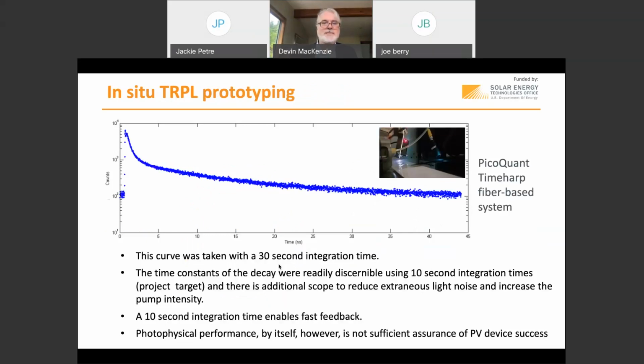We prototyped a PicoQuant fiber-based system. The real key for TRPL was, could we do it fast enough? Could we get enough signal? Our target was a 10-second integration time. So we integrate for 10 seconds, and can we reliably measure a tau, a reproducible lifetime? Because that would enable us to change feedback and process parameters to fix it if the tau is moving too high or too low. If we can get an answer in 10 seconds, we can respond in a few more tens of seconds and bring the process back under control before we end up printing meters and meters of garbage. We can respond quickly with feedback. We actually showed that this is really possible with pretty simple off-the-shelf PicoQuant TimeHarp systems, fiber-based laser delivery, and a relatively large area detector, but nothing super special.